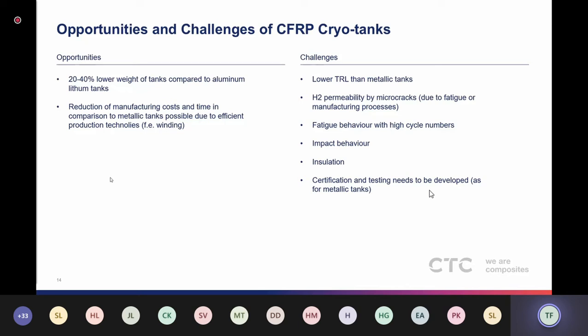But there are also significant challenges we have to overcome. First of all, the TRL for CFRP tanks, the technical readiness level, is definitely lower than for metallic tanks, and there's development needed. One of the major issues is H2 permeability caused by microcracks, also by manufacturing process imperfections, that has to be solved. One challenge is the fatigue behavior, with a much higher number of load cycles compared to the space industry.